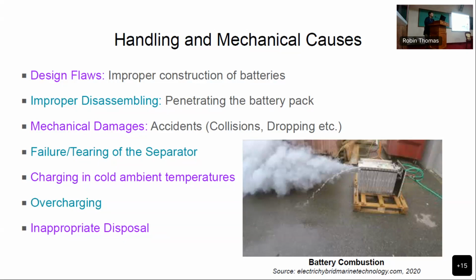Mechanical damage: collisions or high-impact movements, or dropping a phone, for example, also have a good chance of starting a battery fire, because if the impact is high, if there's a lot of impulse, the electrodes might come in contact, and the separator might fail and tear. As we saw earlier, the electrolytes contain organic solvents, so they can decompose to form combustible gases, which will propagate the fire further. And charging in cold ambient temperatures is wrong, because in colder temperatures the lithium will get permanently plated on the current collector.